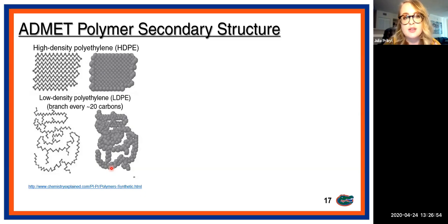So secondary structure is how a polymer is oriented with itself. For example, in high density polyethylene, like in this figure here, the polyethylene segments can line up with each other really nicely to form these crystalline areas, so that it has a highly crystalline secondary structure. And you can do X-ray scattering and a bunch of other techniques on this to determine exactly what the crystal structure of these crystalline regions is.